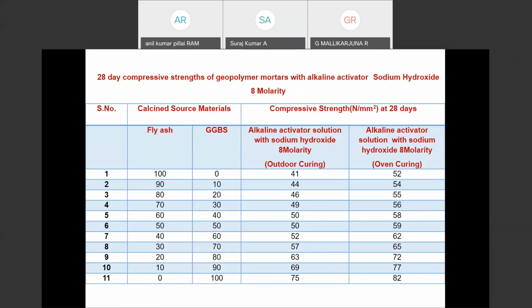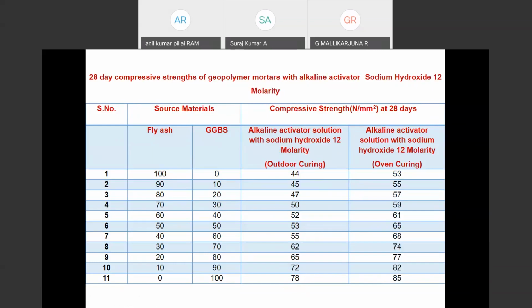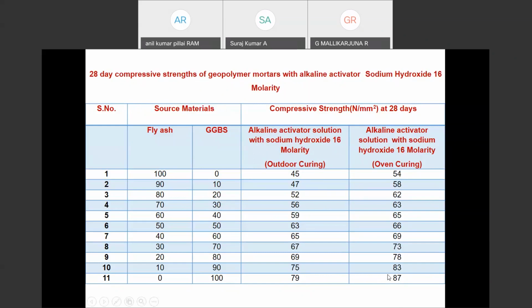Next, we have taken the 28 days compressive strength, for the 8 molar concentration. The alkaline activator solution varies from 100 to 0. Whenever we increase the GGBS content, the strength automatically increases. With oven curing, we get more strength, up to 82 MPa after 28 days of testing of these geopolymer specimens. The same for 12 molarity, it is up to 85 MPa, and for 16 molarity, it is 87 MPa.